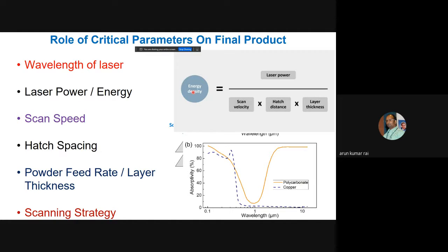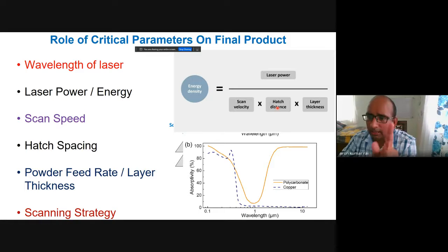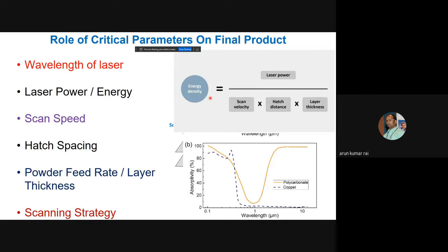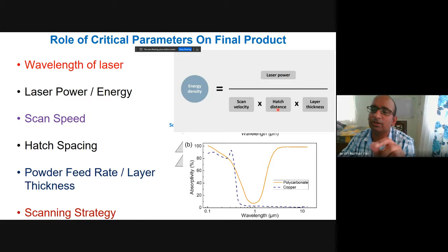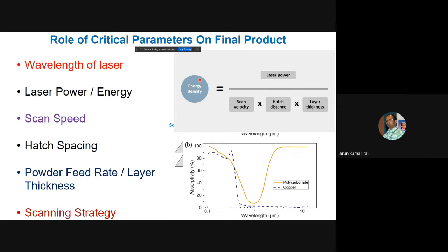If this parameter is the same, whatever you change here doesn't matter. So whenever we report to industry, we report this parameter. Somebody can have a different thickness, accordingly velocity can change, laser power can change, hatch spacing can change, and then different people can report different things. So to avoid this, people look for the energy density. It is a combined parameter which can be uniquely used for a given material. So always the energy density parameter has to be given rather than individual laser power and scan speed, because I can have different combinations of these and produce the same energy density. So one has to look at this.